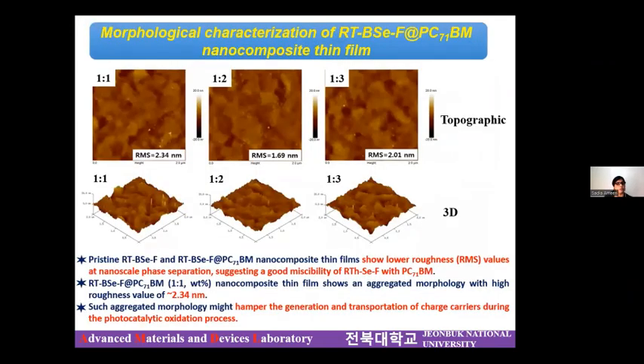And these are the morphological properties which we studied through AFM. What we have found is that for the different composite materials, 1:1, 1:2, and 1:3, all the composite materials show lower roughness values, which itself suggests good miscibility, good solubility of both the moieties, that means the organic molecule as well as the PCBM material. But when the ratio is around 1:1, it shows a certain kind of aggregated morphology. And this aggregated morphology is certainly not good for the application of the photocatalyst, because it might hamper the generation as well as the transportation of the charge carriers during the catalytic performance.